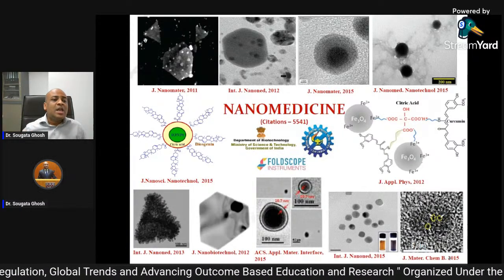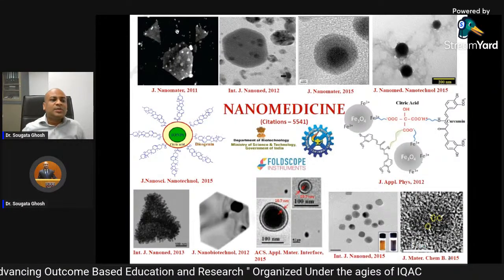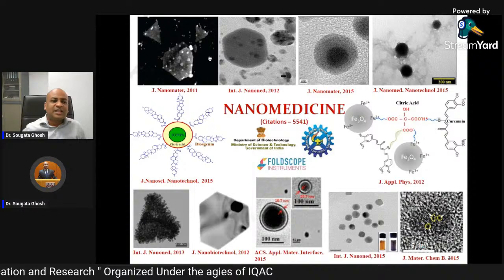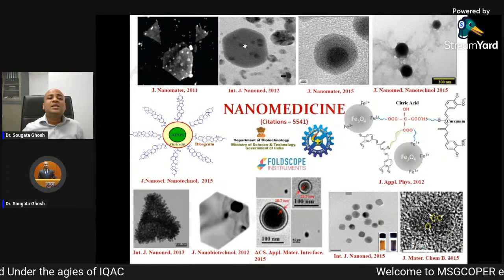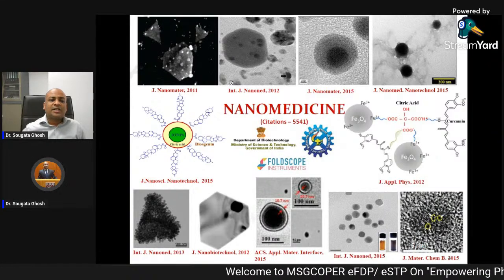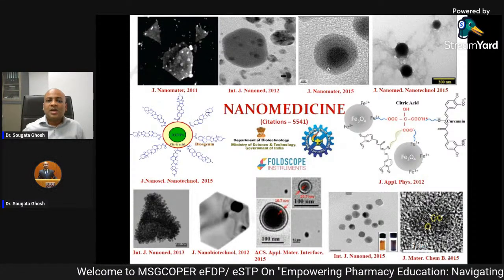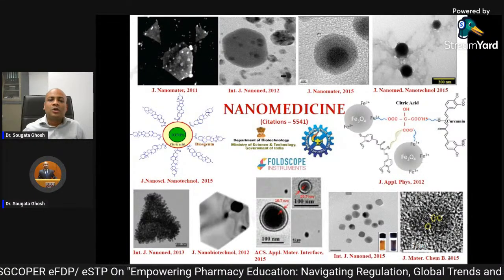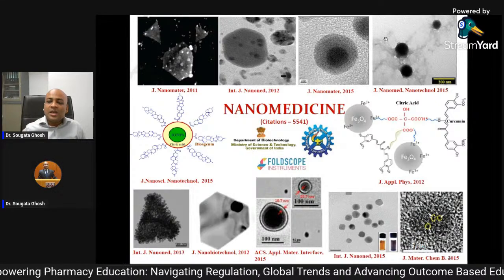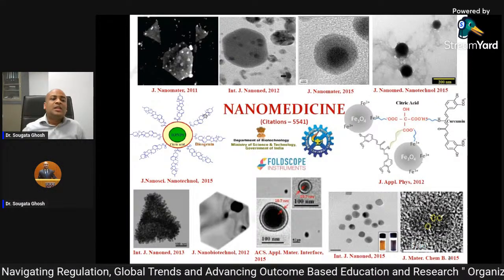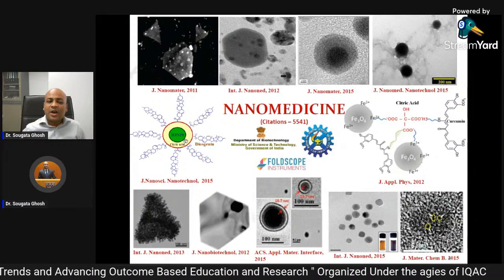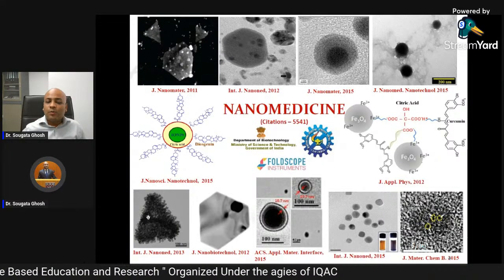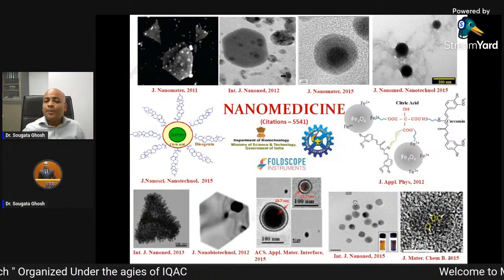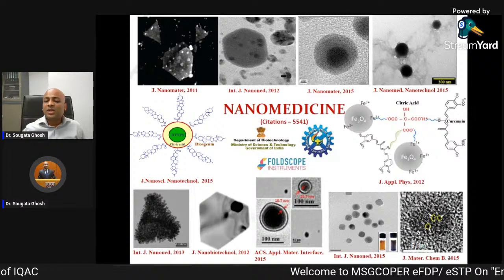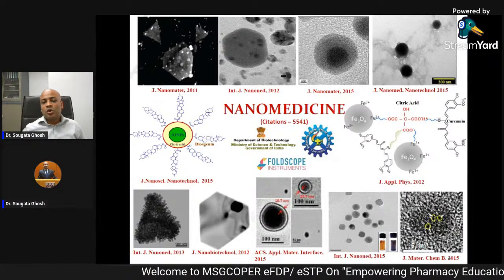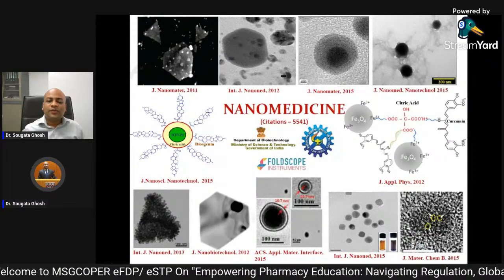So what we are doing over here, you can see this structure, very small spherical nanoparticles, triangular nanoparticles, hexagons, these are gold nanoparticles. These circular or spherical nanoparticles and hexagonal nanoparticles, these are silver nanoparticles. These are core shell bimetallic nanoparticles, gold and silver together. These are copper nanoparticles. These are magnetic nanoparticles. These, you can see iron oxide is in the center. These are gold nanobeads. These are liposomal nanoparticles, palladium nanoparticles, and surface defect rich zinc oxide nanoparticles. So we are synthesizing different types. I will be discussing only a few of them today.